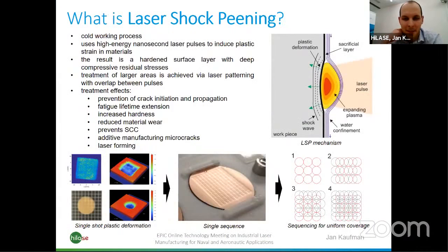So what is laser shock peening? It's basically a cold working process that uses high energy pulses, as we have heard, nanosecond laser pulses, to create plastic strain, which in turn creates very deep compressive residual stresses. So the way it works is that the laser pulse comes from the right over here. It is focused onto the workpiece, which is covered by some kind of sacrificial layer. It can be black paint, it can be black tape. And there's also a thin water layer flowing on top of it. The laser pulse is absorbed and plasma is created.